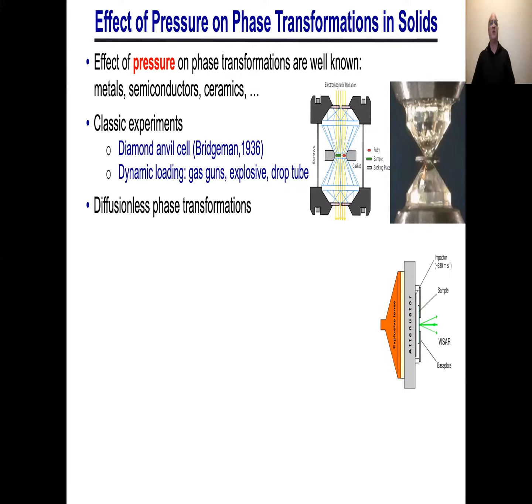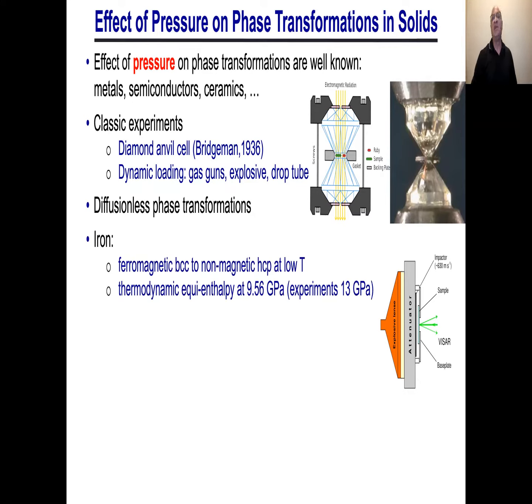And in particular, what I'm going to be talking about is diffusionless phase transformations. Just to give you a few examples, if you look at iron at low temperature, so iron's body centered cubic, as we all know, under normal atmospheric conditions, at room temperature. If you squeeze on it hard enough, it goes into the epsilon phase, which is the HCP phase. And it's obvious why it does that, because the close packed structure there has higher density. So when you squeeze on it, you thermodynamically shift the phase equilibrium. And if you do DFT calculations, you can estimate the transition should happen at about 10 GPa, but the experiments typically show some higher value, and I'll come back to that in a minute.